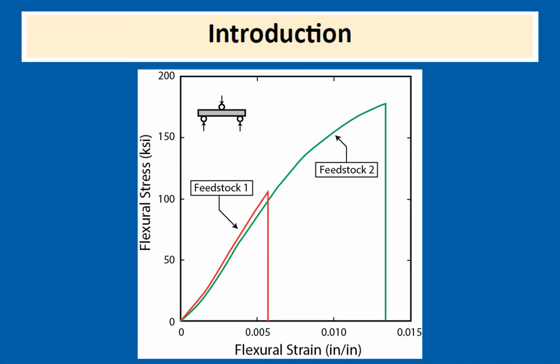Three-point bend test data revealed that the hydrogen-rich coatings displayed lower strength and far more brittle behavior. While there was a difference in particle size distribution, the initial hypothesis was that the hydrogen content played a dominant role in the bonding and deformation mechanisms during cold spray processing, and it was consequently the focus of this study.